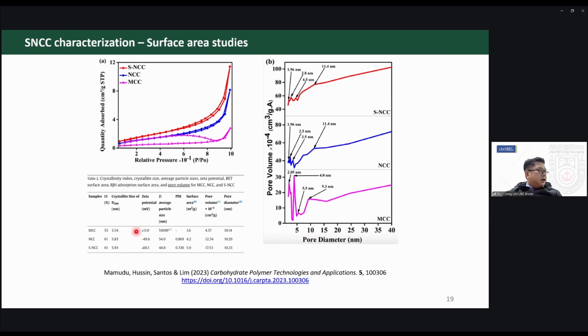We also did some study on the zeta potential, and we confirmed that the sulfated nanocellulose has a more negative zeta potential, indicating that our negative charge hypothesis was actually working.